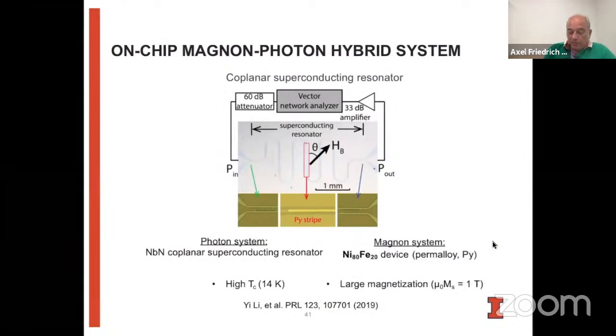So the photon system consists of a coplanar superconducting resonator that's made of niobium nitride. We use niobium nitride simply because in our group at Argonne, we actually had quite some expertise in making nice microwave devices out of this material. And one of the advantages is that the TC is rather high. It's 14 Kelvin. And so what that means is the cutoff for microwave frequencies that you can use is actually much higher than if you were to use aluminum. Also, it means by going to the same temperatures, you just get much higher quality microwave devices than you would get with aluminum on its own.